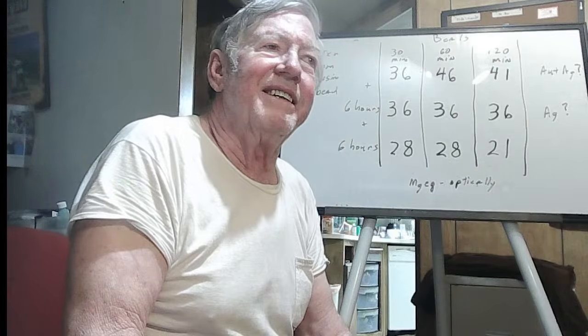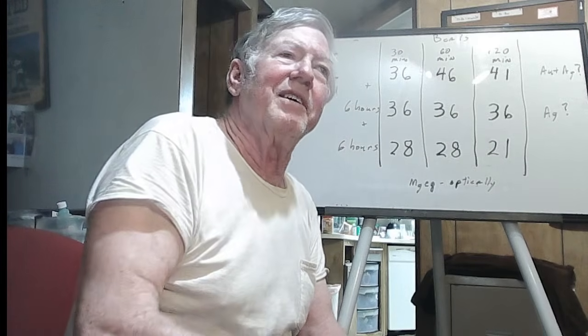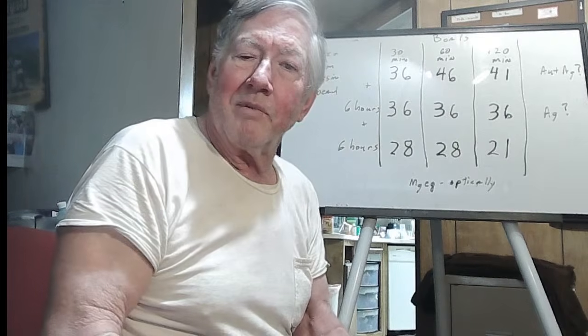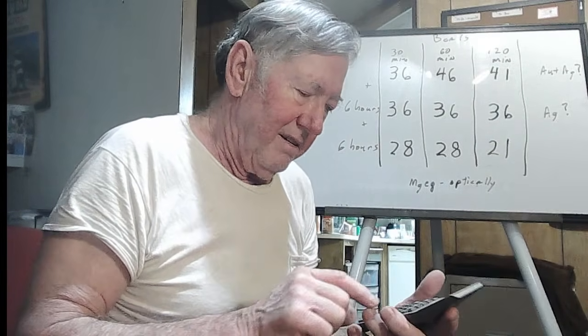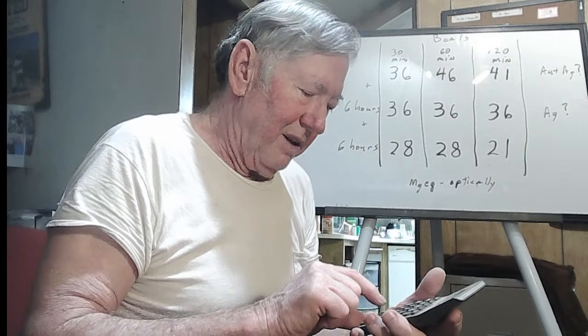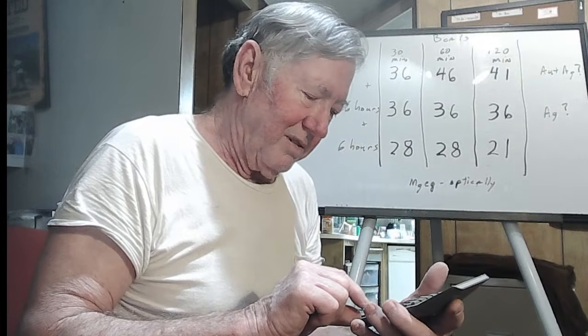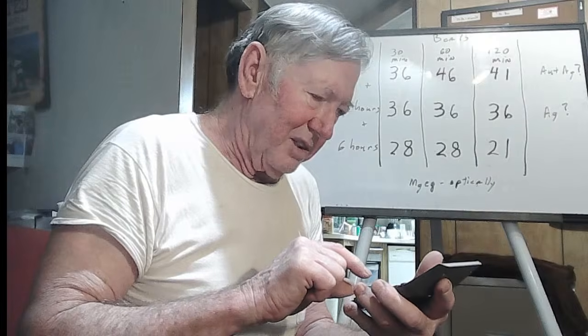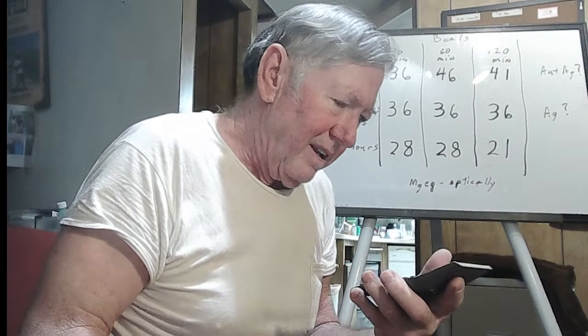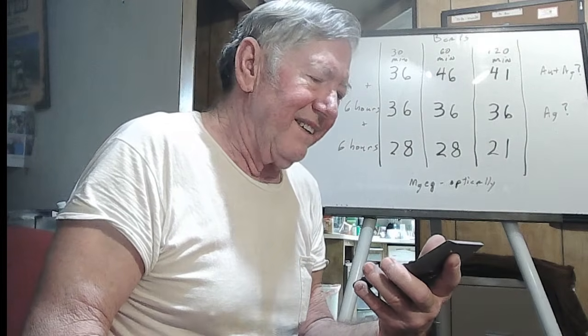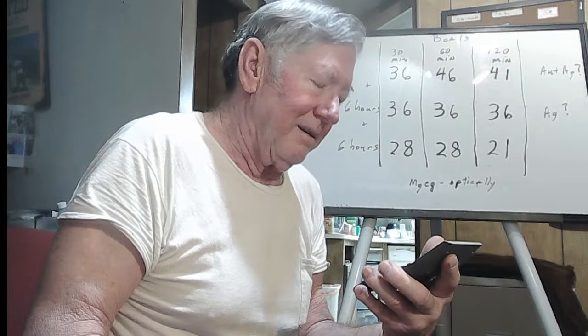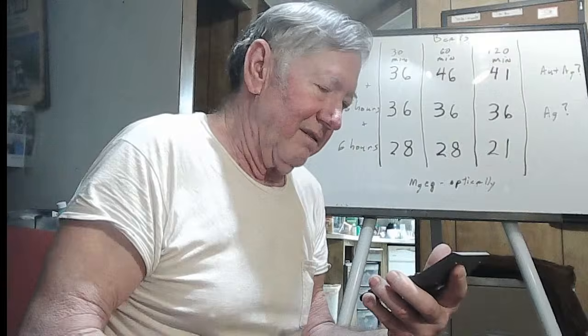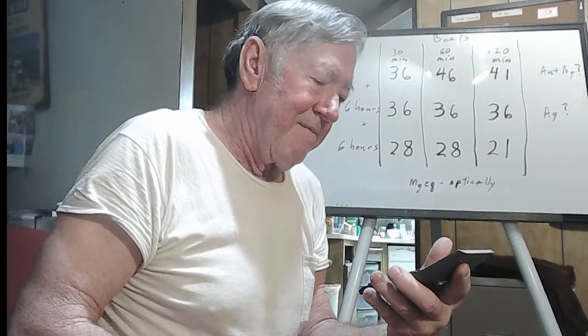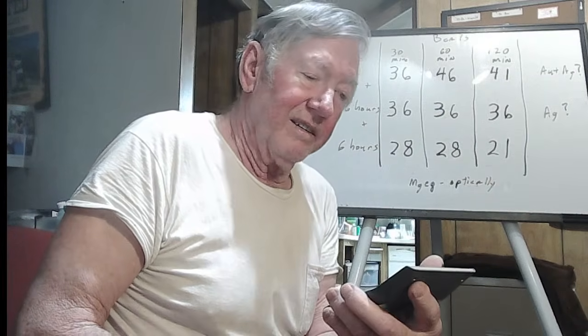The test we did previously seemed to indicate that the gold rapidly dropped to about 9 parts per million and then just flatlined. So if you had 9 parts per million in solution, and you had 25 kilograms, and you had a 3-to-1 solution ratio, you would have 0.67 grams in the solution. Yeah, 0.67 at 10 parts per million. Okay, 9 parts.